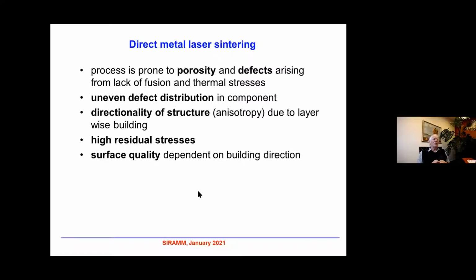Important is also uneven defect distribution in a component. If we have in a component some place where defects concentrate, and simultaneously this place is loaded by cyclic loads, it may be dangerous. A problem is directionality of structure. It means anisotropy. This anisotropy is due to layer-wise building of this material. Generally, in this technology a big role is played by high residual stresses in the component and naturally surface quality, which is dependent on the building direction and which again strongly influences the fatigue behavior of materials.